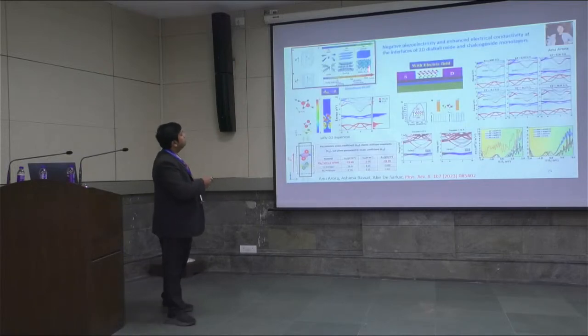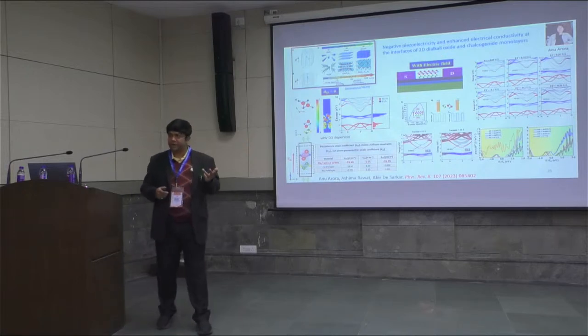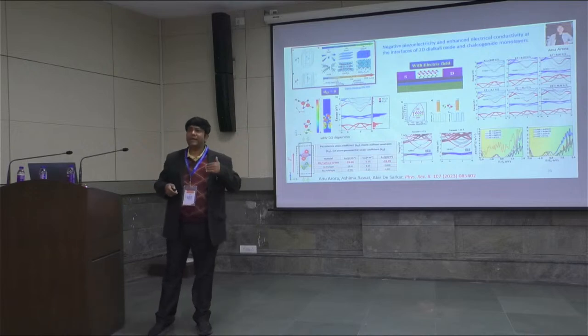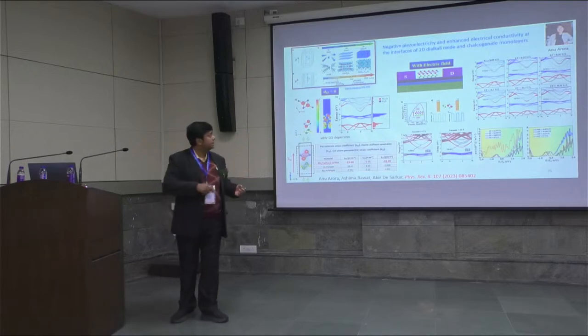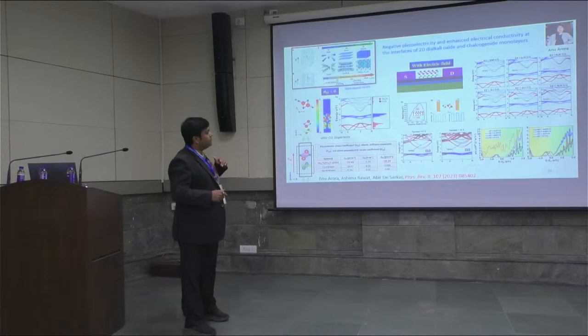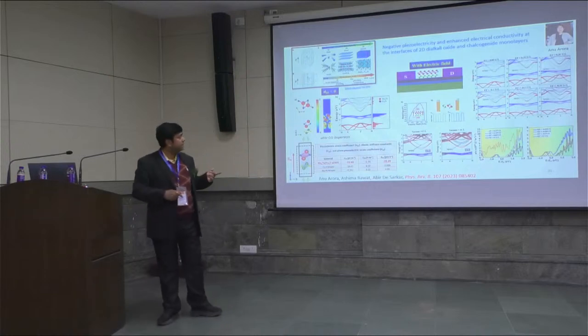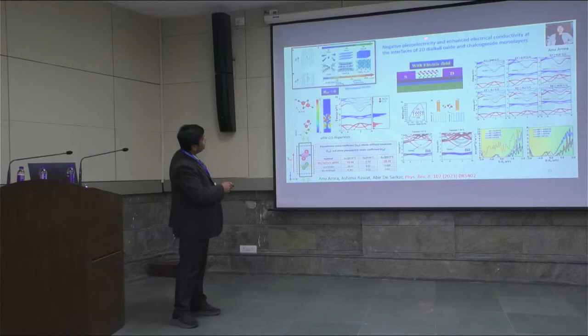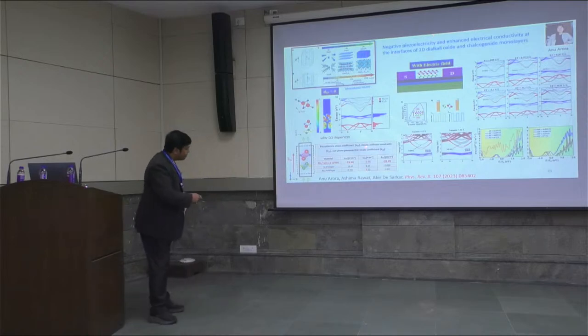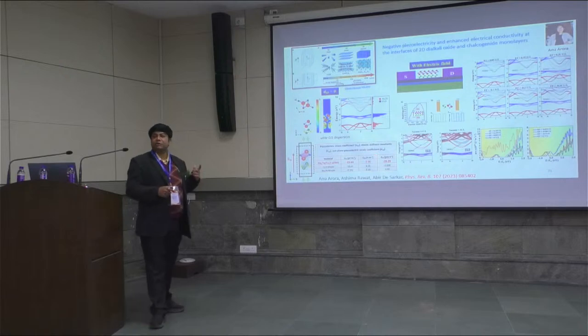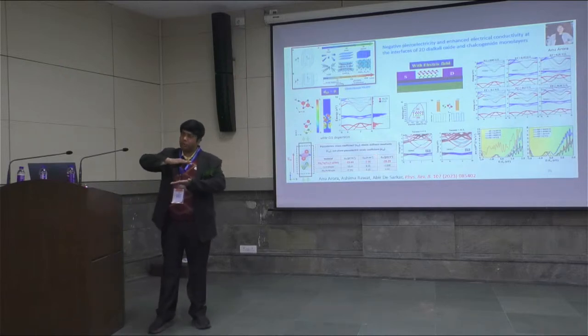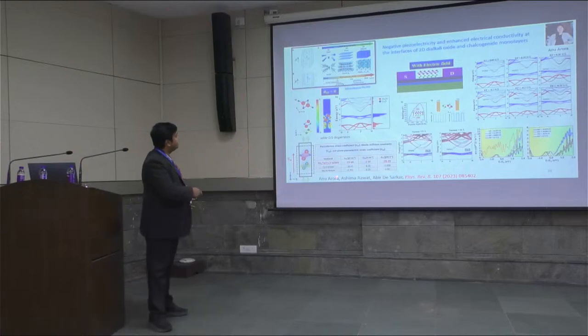So now we usually calculate the piezoelectric coefficients. Experimentally, we measure the piezoelectric coefficients, but we usually ignore the sign of the piezoelectric coefficients. The sign of the piezoelectric coefficients can be important even from fundamental perspectives. So we have ascertained the origin of the negative piezoelectric coefficient. We find that it arises from a small out-of-plane elastic stiffness constant. In van der Waals hetero bilayers, you have a small out-of-plane elastic stiffness constant. So that gives rise to a negative out-of-plane piezoelectricity. That is what we find over here.